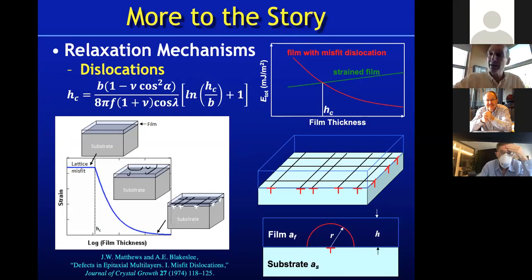So let's talk about the first limit. It's great to be able to strain things by huge amounts, and you can be thinking about how that's going to affect the band structure and give rise to all sorts of new phenomena. But nature, of course, is always going after the lowest energy state. So when you strain a material, you increase its energy. And the green curve that I show here is showing, as a function of film thickness, how straining increases the energy. As you make it thicker, you have more and more volume, and that strained volume costs you more and more energy. So the energy goes up linearly as you increase the thickness of the film.